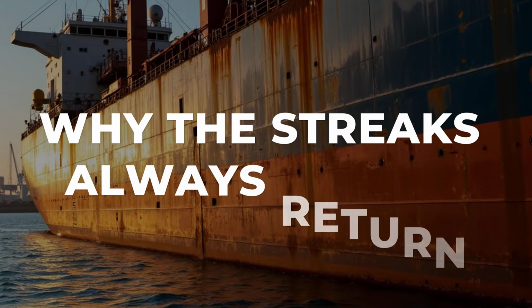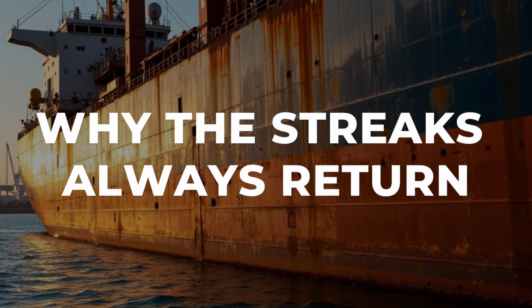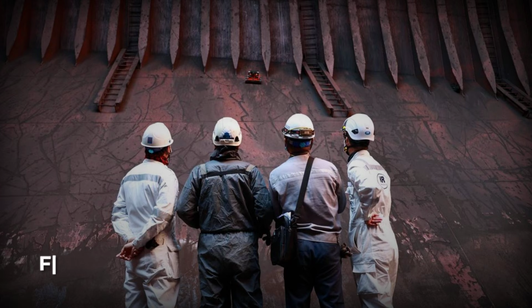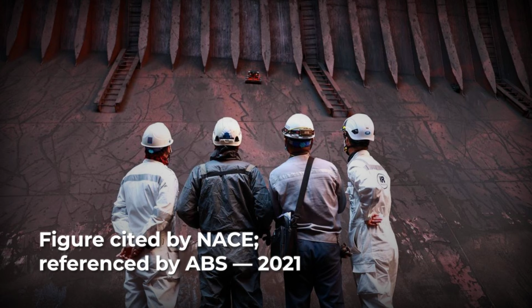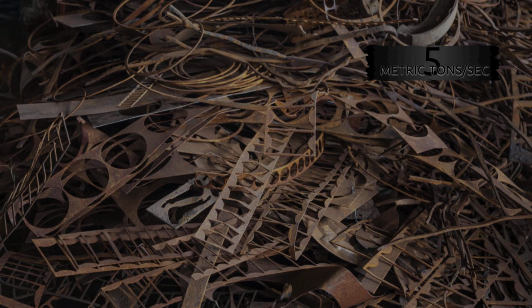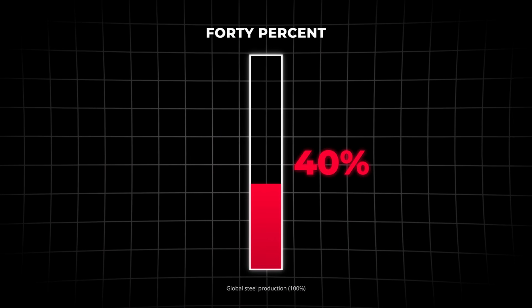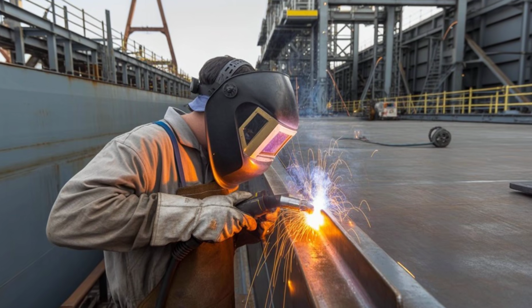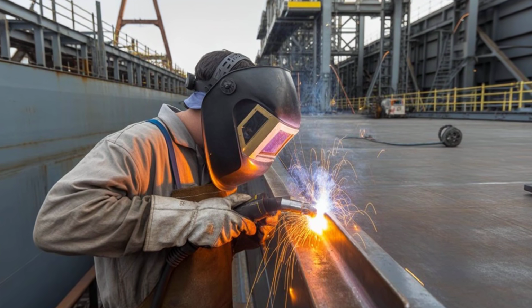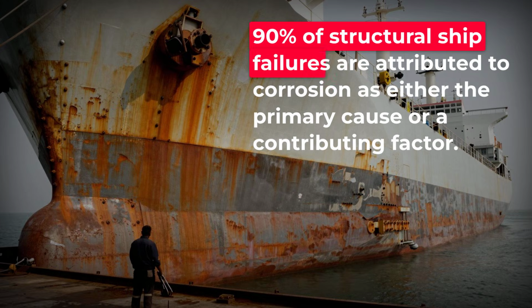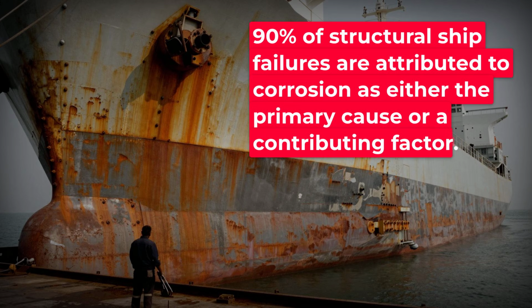Corrosion costs the global maritime industry $50 to $80 billion every year, a figure cited by NACE and referenced by Classification Society, ABS, in 2021. Globally, 5 metric tons of steel disintegrate every second. 40% of all steel produced worldwide exists solely to replace steel that has already corroded away. 90% of structural ship failures are attributed to corrosion as either the primary cause or a contributing factor.